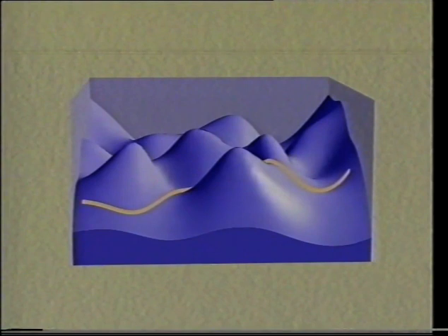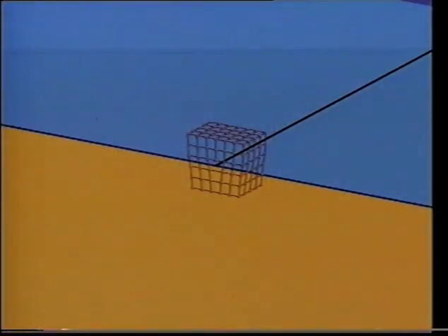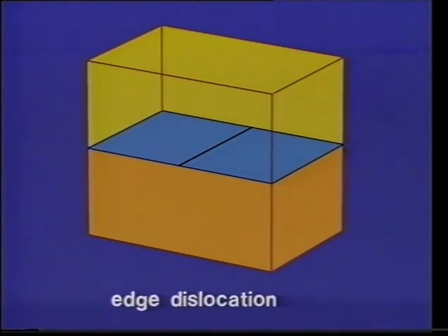Earlier, we saw a dislocation moving in a two-dimensional model. Now let's consider some of the ways in which the length of a dislocation line moves in three dimensions. Let's consider glide in more detail by returning to our picture of a dislocation. You will recall that this type of dislocation, located at the edge of an extra half-plane of atoms, is an edge dislocation. Its Burgers vector is perpendicular to the dislocation line. The dislocation is able, under an applied shear stress, to glide in the plane which contains itself and its Burgers vector. This is the slip plane.